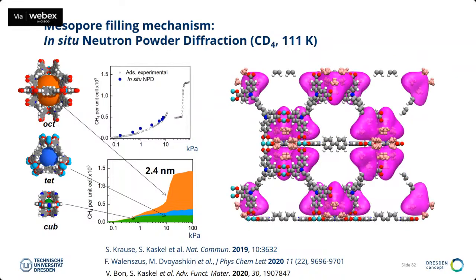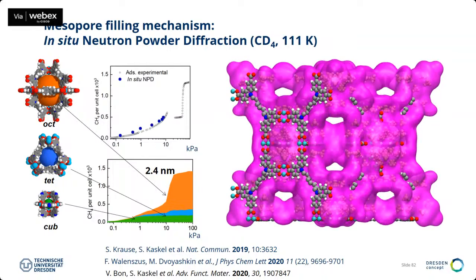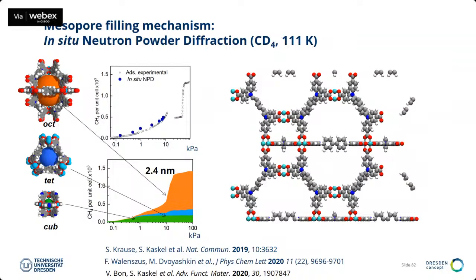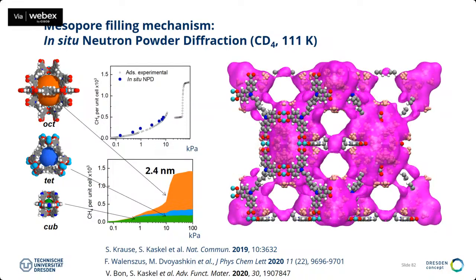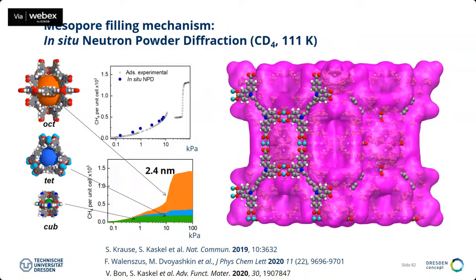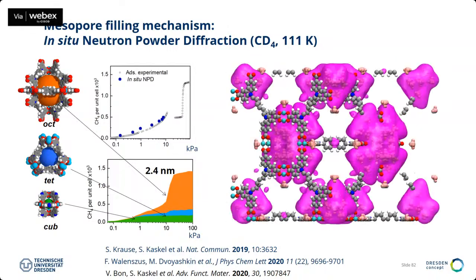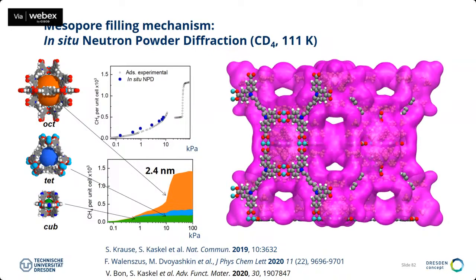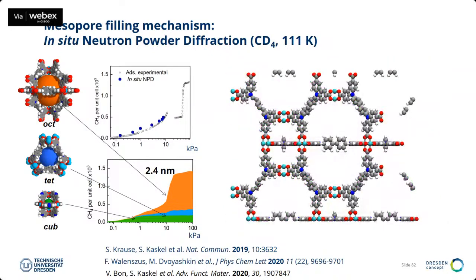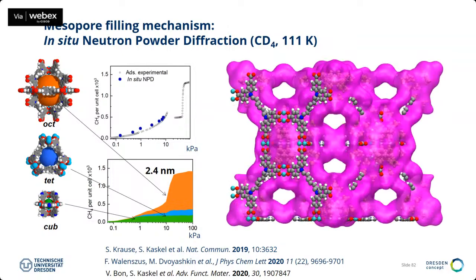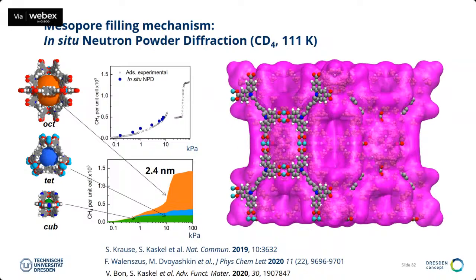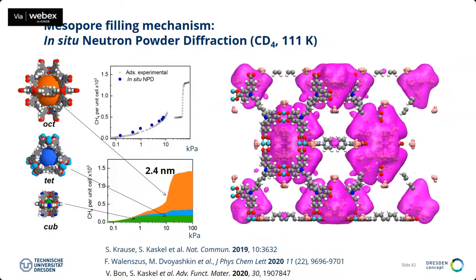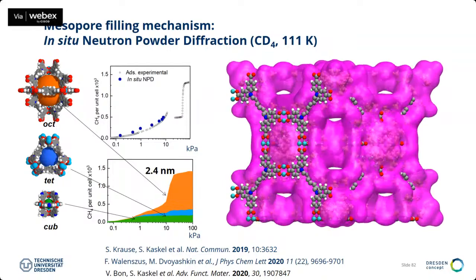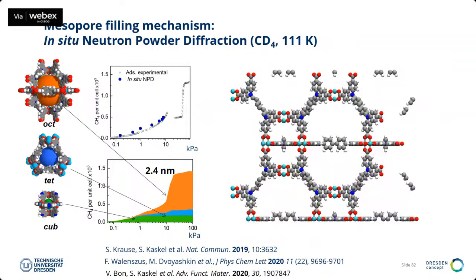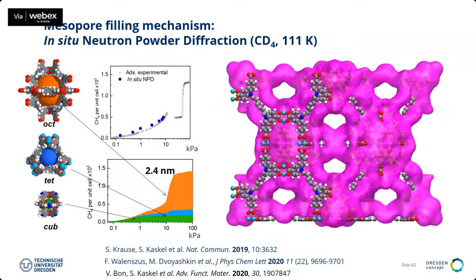Here we localized all the methane molecules in the deuterated form inside the pores. And this was also quite interesting because what we realized is that when you enter this negative gas adsorption step, the small pores and also the intermediate pores are almost completely filled. But what is really starting to fill is this large mesopore. And this is probably one criterion also to find new negative gas adsorption materials: you have to have very large pores, pores that are larger than 2 nanometer, to find these kinetic barriers. And probably they are also associated with kinetic barriers of the fluid, not only of the solid.